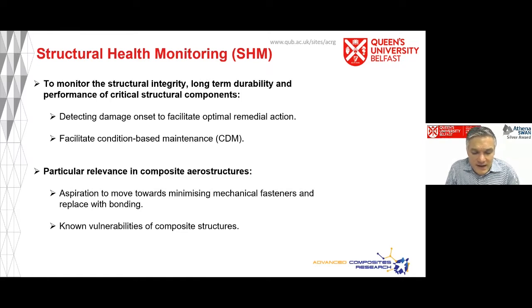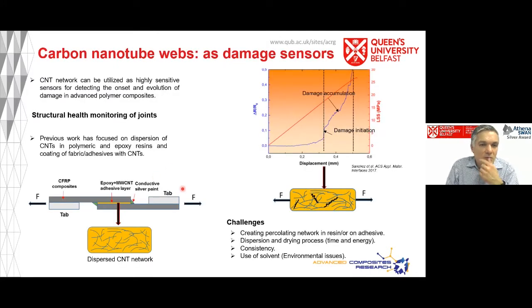Now, this has been looked at by a number of researchers. For the most part, researchers have tended to disperse carbon nanotubes into an adhesive, and then look at some percolation threshold where you've got enough carbon nanotubes there to give you some sort of conductive resin or conductive adhesive, and then you can look at the changes in resistance, say if you put this adhesive in a joint. When you do that, you do get a change in resistance with the accumulation of damage, as you would expect.